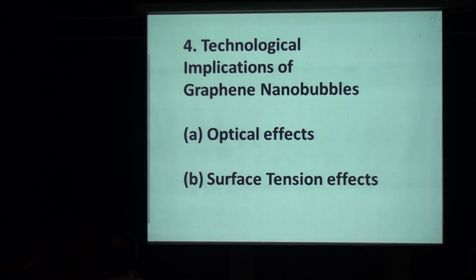Optical effect. Normally, when you have flat graphene and you shine light perpendicular to it, or if you have the graphene vertical and you shine light along the plane of graphene, the light-matter interaction will be different. Now, for flat graphene, because it's so thin, there's very limited absorptive path length. You cannot expect the graphene to change the optical path of the light. It's only one atomic layer. But once you form bubbles, you have extra vertical sidewall, in the vertical dimension, so you increase light-matter interaction.